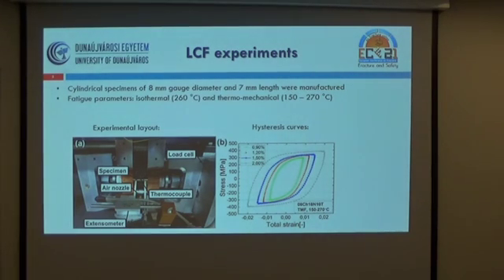We produced cylindrical specimens with 8 mm diameter and 7 mm length, and we tried to simulate the operating conditions. Low cycle fatigue can occur in the reactor pressure vessel during heating up and cooling down, which belong to the normal operation, plus sometimes during some accident conditions. And we performed isothermal low cycle fatigue experiments and thermomechanical experiments.